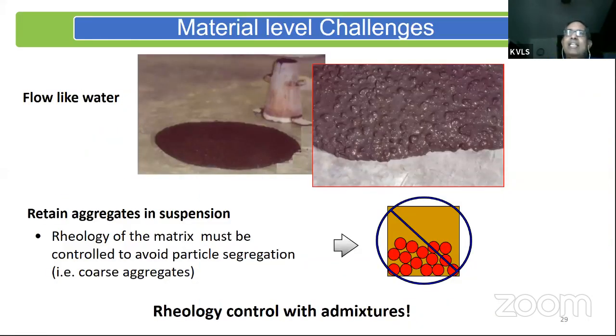If I look at concrete, it is made up of cement paste and aggregate. Now, how do I get concrete to flow? One of the easiest ways for me to do it is to increase water content. The minute I increase water content, my cement paste becomes less viscous and my aggregate starts segregating. So the minute I start adding water to concrete, my aggregates all start settling to the bottom. That's because the viscosity of the cement paste has decreased. So now how do I increase the flow while I retain my aggregate in suspension?